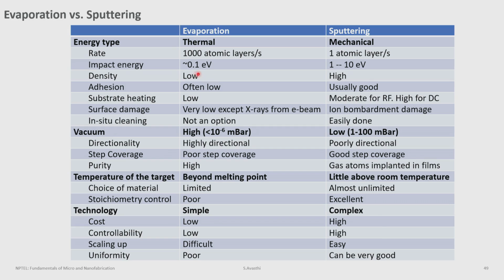The density of films in evaporation is low. In sputtering, you can make it high, because by just bombarding the surface, you can enhance the density. The adhesion of films can sometimes be low in evaporation. In sputtering, it is usually good, again because it's a bombarding type of process. It tends to have good adhesion. The substrate does not heat much in evaporation. It can heat in sputtering because of the bombardment of argon plus ions, especially during RF sputtering.